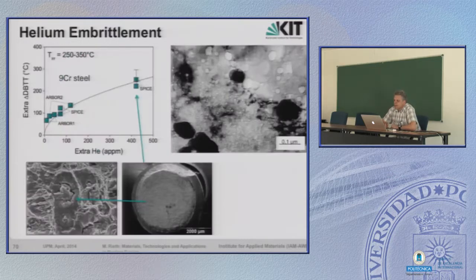The same has been done with a different type of material where extra DBTT by helium formation was measured, and with rising helium content, the shift of DBTT increases, that's clear. This is how such a rather brittle fracture of a tensile specimen looks after it has more than 400 appm of helium. The microstructure looks like here. You can see millions of tiny helium bubbles.